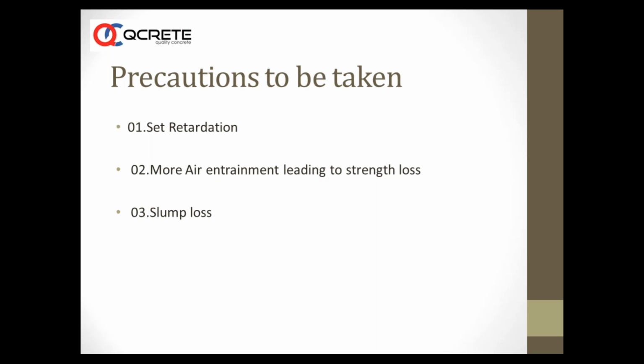Set retardation is a common problem for any concrete producer or many of the ready mix companies, generally caused by more dosage if the calibration is not done, or something like that. Some of the cements may have low C3S, or low C3S to C2S ratios. Some cements, if older and already absorbed some amount of moisture, and if you are adding a type G admixture at the same dosage used earlier, then also it can cause retardation. Some organic matter can cause set retardation. So we need to be careful about these things.